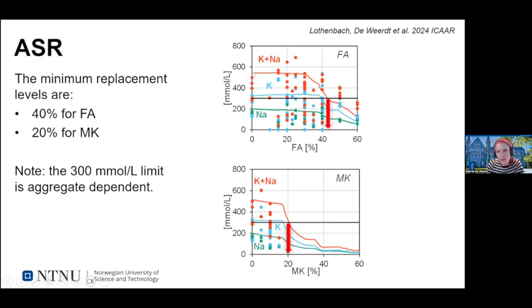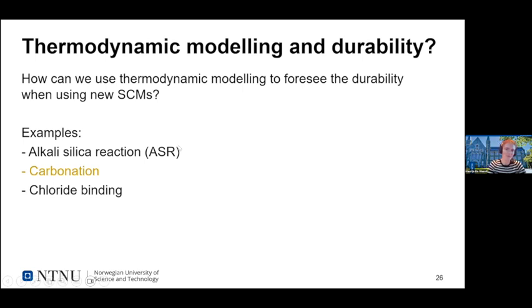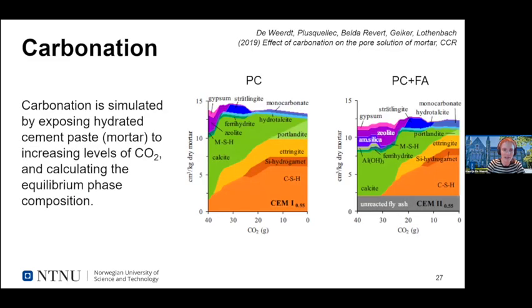And what we can see is that for fly ash, the total alkali concentration in the pore solution drops below this 300 millimole per liter at a replacement level of approximately 40%. Whereas for metakaolin, this already happens at a replacement level of 20%. So this gives an indication of how much of an SCM we need to include in our system to try to mitigate ASR. And there GEMS can be a very neat tool. So this was an example for how we use thermodynamic modeling to predict potentials of ASR and the impact of SCMs.